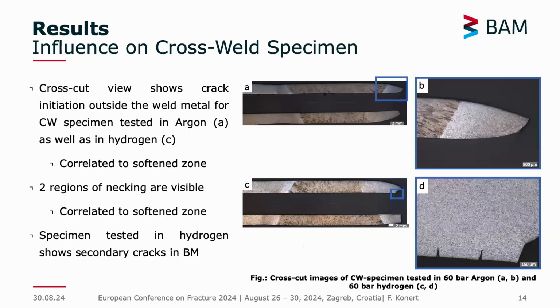So, and just to get a closer look at the location of the fracture, we performed these cross-cut images, and as you see on the top, you see the reference of the cross-weld specimen, and you also see in this cross-section image that you have a clear necking in the specimen, and also this 45-degree crack is present here, and the crack is just outside the weld metal. This is just because we have a slight overmatch in the weld metal, but for hydrogen it's nearly the same. So we also have the crack initiation outside of the weld, but we have some secondary cracks here, and also the orientation of the crack is slightly different. So yeah, these are more or less the results of the cross-weld specimen.